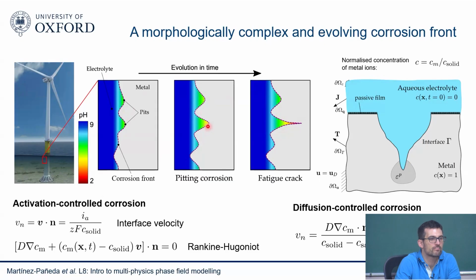Okay. So the governing equation and what you assume for, let's say, a normal sample under electrolyte of sufficient depth, versus this one where oxygen exchange is much more rapid because your film thickness is only so much for the electrolyte. You're saying because you're in this zone where you have water and oxygen because you get waves, or is that what you're thinking? Or your electrolyte, the water droplet through which this atmospheric corrosion happens, is very small. So you're referring to the fact that we're not deep in the sea. The most harmful environment is this kind of condition here. Exactly. Yeah, we've done some simulations where we account for this. I don't know if I included many slides about it, but if there's time, I can bring them from a previous talk. We are looking into that also in the context of, for example, concrete corrosion, where you may have a bit of rain and then a very small thin layer. So you can also do those things.